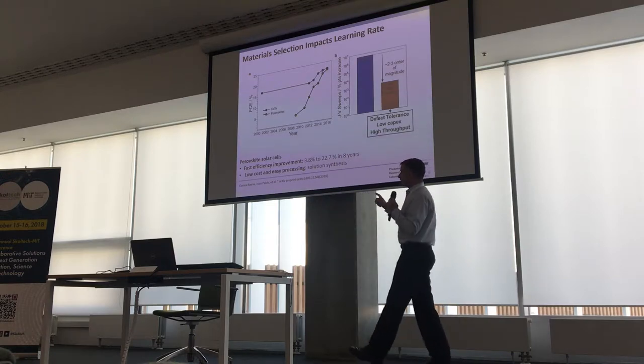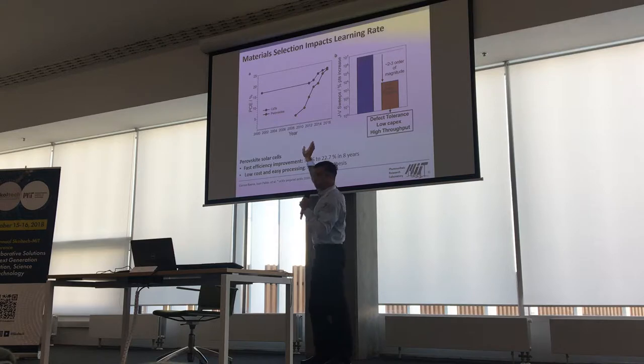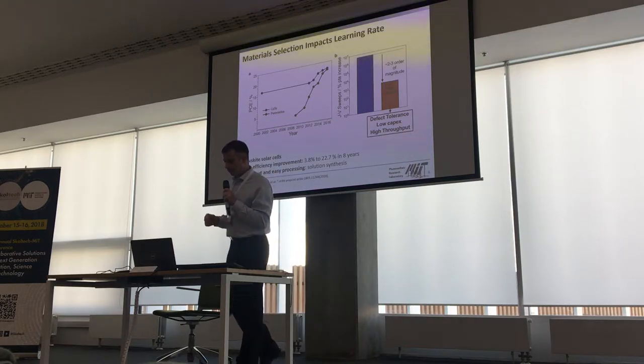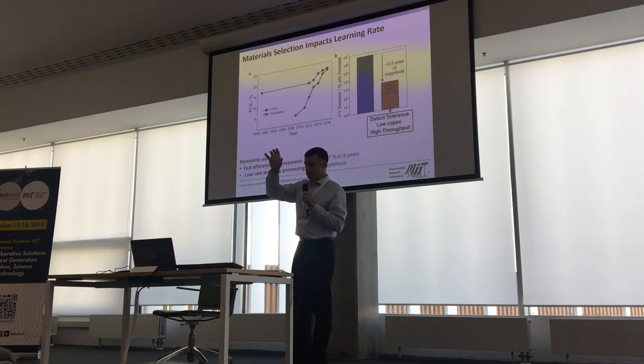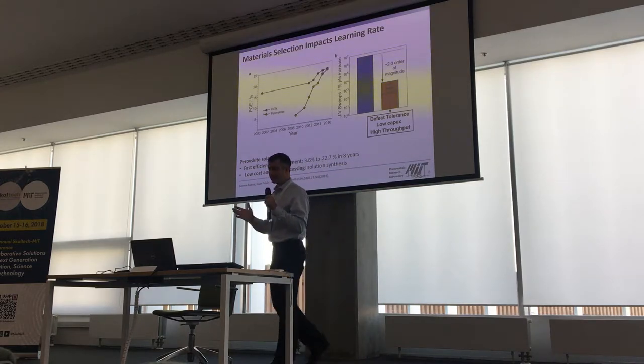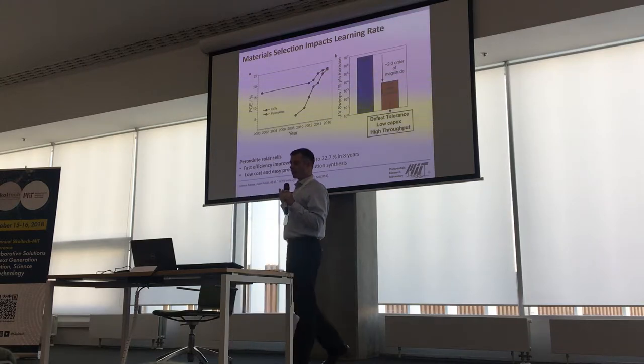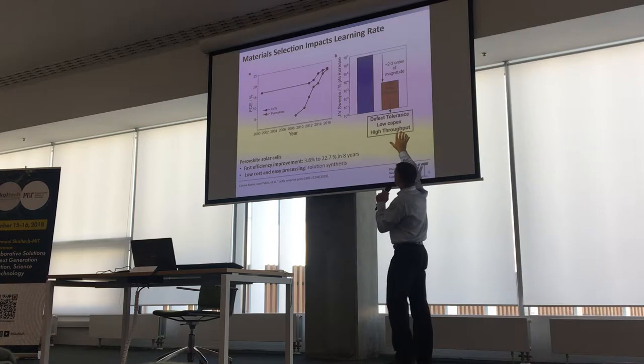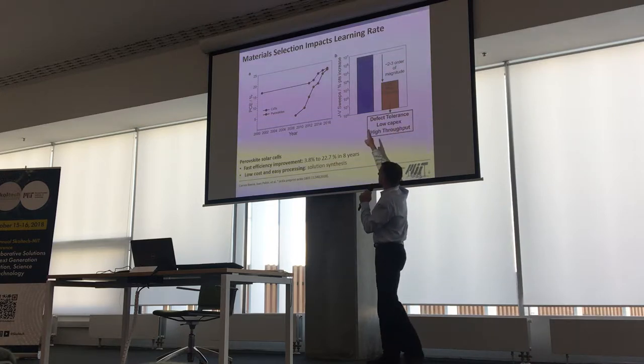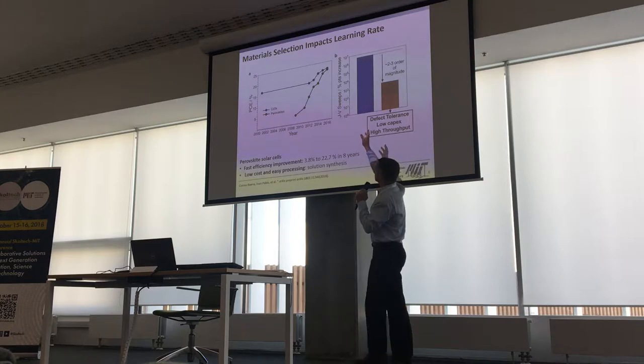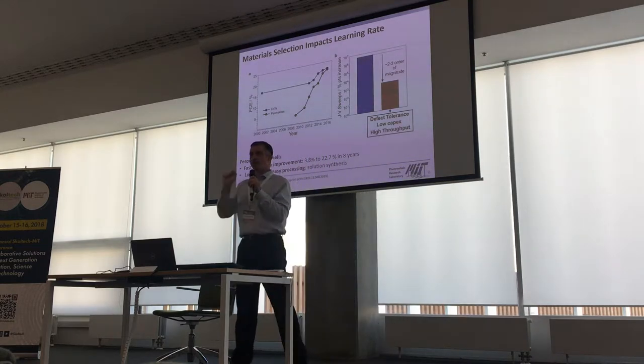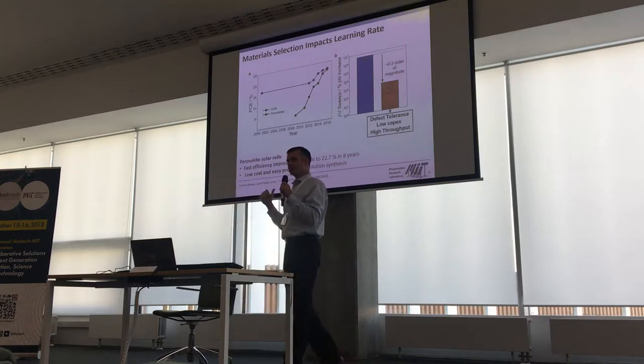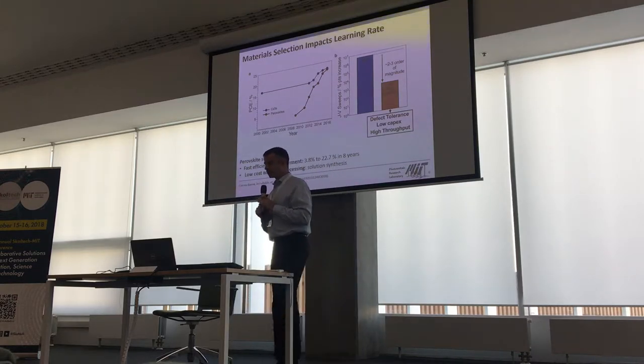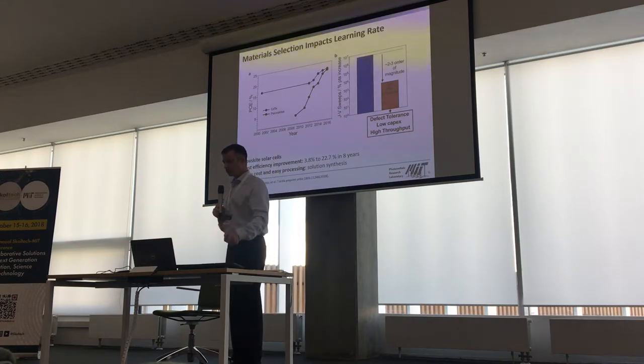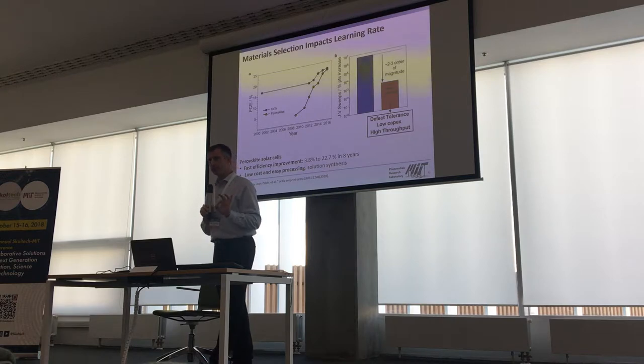If we look at cadmium telluride in blue and perovskites in red, this is the lead halide perovskites, the efficiency versus time. What we notice is that both have tracked similar efficiency improvement curves over the last half a decade. And the work or effort needed to improve the efficiency of the perovskites was around 2 to 3 orders of magnitude less than the cadmium telluride. So CdTe required around 1 million to 10 million current voltage sweeps per percent efficiency improvement, and the perovskites were 2 to 3 orders of magnitude lesser. So it's not just that we grow samples faster in the perovskite community. There was something intrinsic about the material that made it more defect tolerant, more amenable to this high rate synthesis platform.